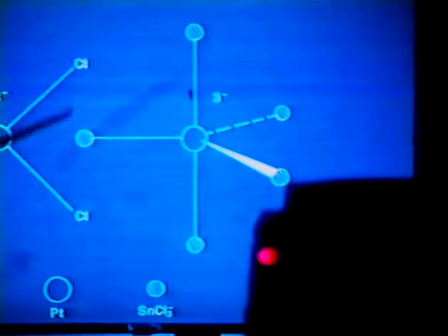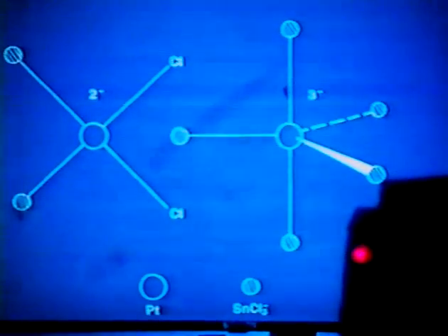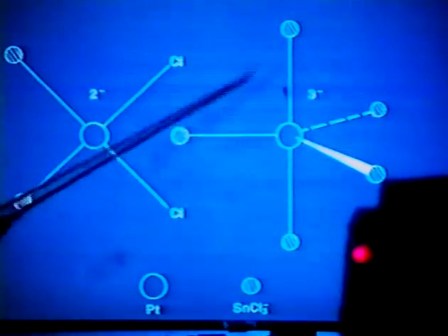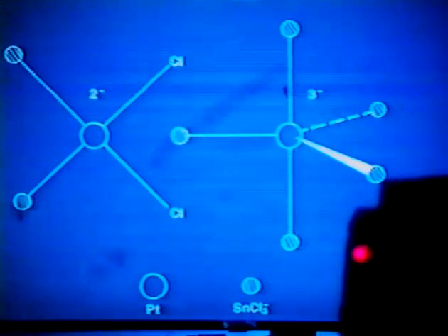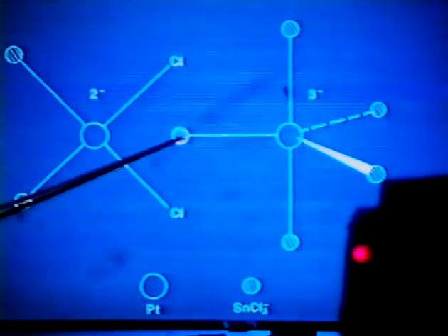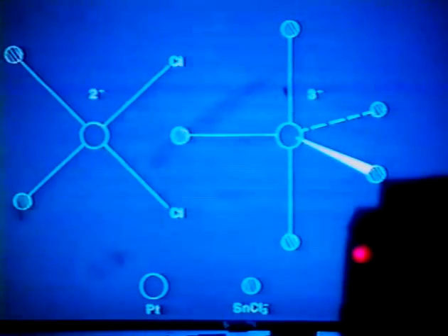What I've shown here is just some structures. These are platinum-tin coordination complexes. We've got a platinum atom at the center in both cases. Over here we've got SnCl3 ligands out here, and chloride ligands out here, and there's got to be 2 cations around. And over here we've got this interesting trigonal bipyramidal platinum-tin-5 complex. It's got platinum at the center and 5 of these SnCl3 ligands out around the perimeter. These things are simple to make. If you mix stannous chloride and hexachloroplatinic acid, you'll end up with these things. They're easy to crystallize and do X-ray diffraction on or anything you like. But they have got this short platinum-tin bond, which is well characterized. That's the kind of bond we see in our catalysts, and tin-2 is the kind of tin we see in our catalysts. Next slide.